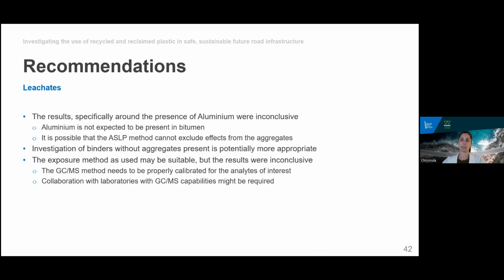Since we were able to detect leachates such as aluminium, which is not expected to be present in the bitumen or any of the additives, both in the crushed and uncrushed loose mix asphalt, we cannot confidently express that the method can exclude the effects of aggregates. Therefore, we conclude here that a method for investigating the binders before they're mixed with the aggregates is potentially more suitable. We note, of course, that the method described here did not bring forward any relevant readings. Now, this could either be because no leachates were present in the samples or because the method was not calibrated to the analytes of interest. We feel that this method still warrants further investigations.